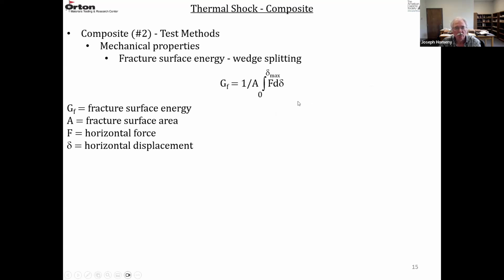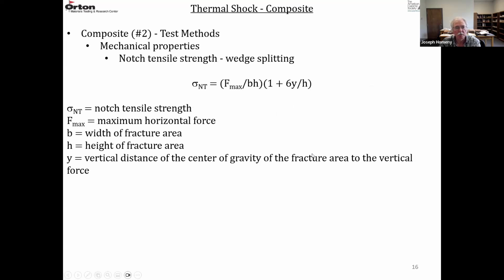So again, this is the formula for the wedge splitting. GF is again the fracture surface energy, A is the area, F is the horizontal force, and delta is the horizontal displacement. So in this wedge splitting test, you get other information. You can get a notch tensile strength. So sigma NT is the notch tensile strength. That equals F maximum, so that's the maximum horizontal force. B and H are sample dimensions, the width and the height of the fracture area. And Y is the vertical distance from the center of gravity of the fracture area to the vertical force. And that's where the cylinders transmit the load to the wedges.